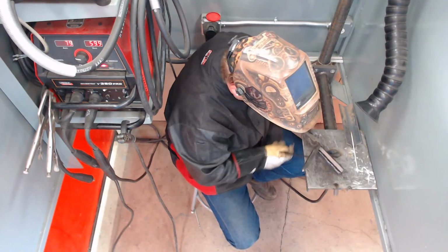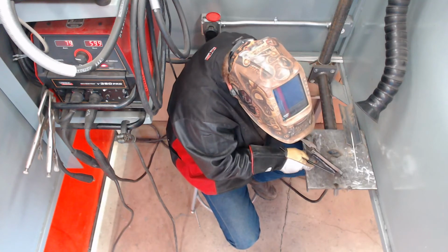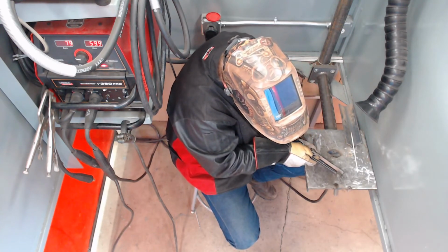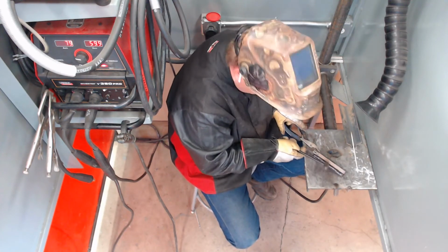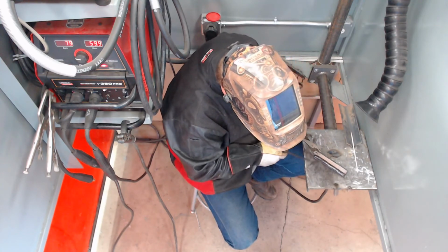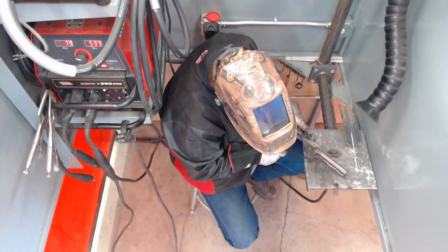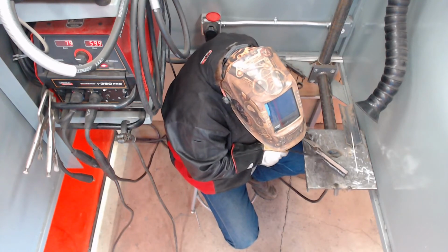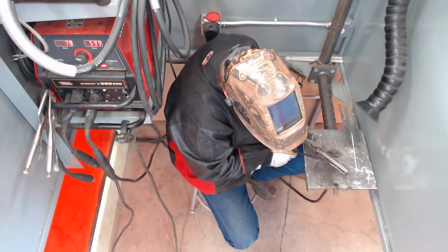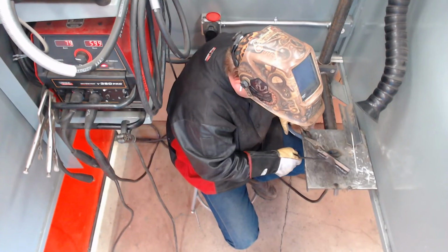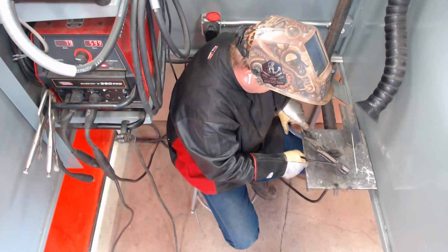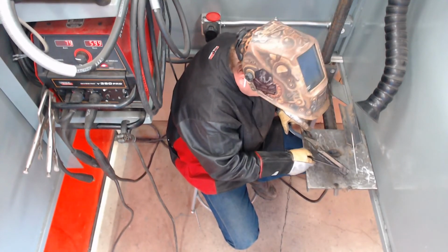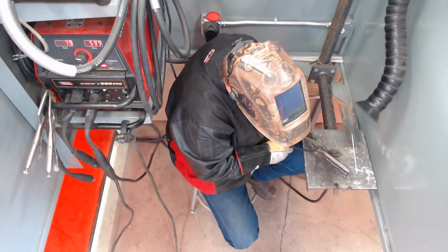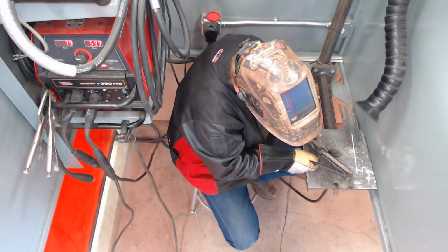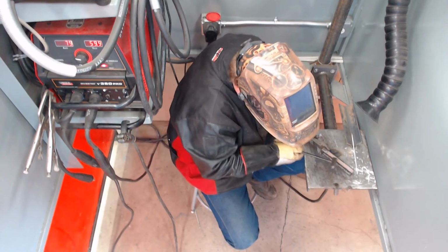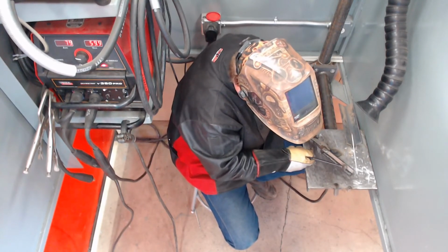This pass is probably the most treacherous because there's a tendency to get slag trapped right in here, between the top toe of the weld and the top piece of metal. So you must be very careful not to get slag trapped inside there. Again, if you need to take it out and hit it with a wire wheel, that's all good.